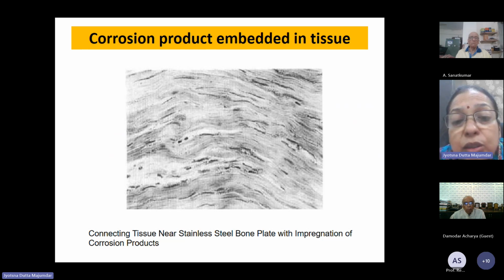It is very difficult to simulate the situation, but mostly it has been observed that fretting corrosion is the predominant mode of corrosion, in addition to tribocorrosion in fretting mode, which causes maximum problems associated with dental implants. But if you talk about hip and femoral prostheses and knee joints, in addition to corrosion, fatigue problems are also there, which cause degradation or premature failure of the implants. So this is the connecting tissue near a stainless steel bone implant with impregnation of corrosion products.